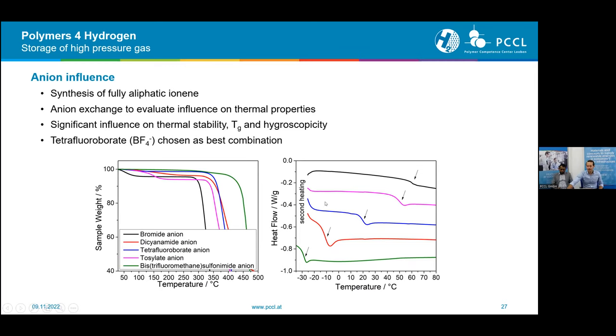From those results, I'm not going into detail for all the different anions, but we needed to find one that combines the properties the best. So we chose this tetrafluoroborate anion here in blue because, on the one hand, it provides a very good thermal stability with rather low hygroscopicity. So there's a rather low mass loss for water, but it also does not decrease the glass transition temperature as, for example, the